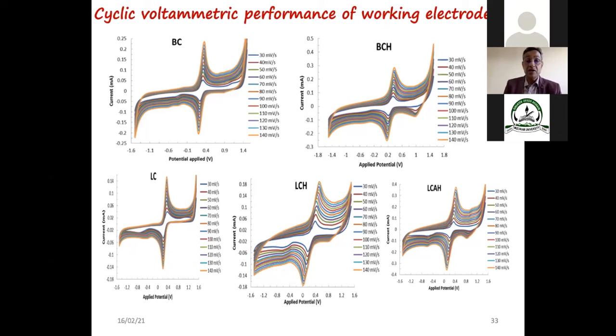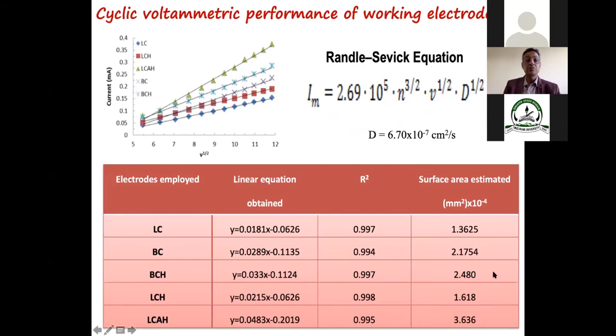Okay, so if the electrochemical signals are increased, that means the detection limit that you will be getting is up to a much lower limit. So that is the advantage of this. Using this Randles-Sevcik equation, where Ip is the current which has been measured, and nu to the half is the scan rate. If I plot this scan rate against this current, the rest of the quantities are constant except this A. C is the concentration, a constant concentration that we have taken. D is the diffusion coefficient of this iron, that standard value that we have introduced. So from here, A can be calculated. This is the slope of that. Okay, so A was calculated.